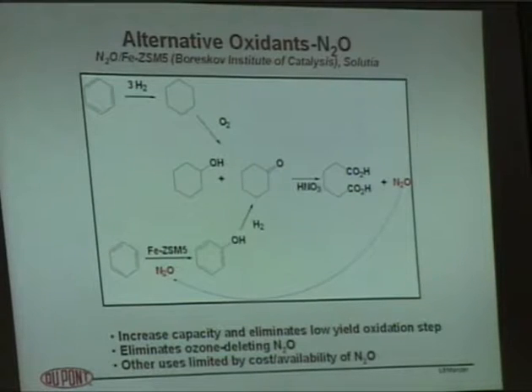And what's very neat about this whole process, reported by Panov, is that this alpha oxygen is very stable and very reactive. And in fact, he reports that you can take this alpha oxygen on the surface down to as low as, I think, minus 40 degrees centigrade, and still react that alpha oxygen with benzene to give phenol. So it's a very, very reactive, very stable site on the surface. So that's the mechanism proposed by Panov and the Solutia group.